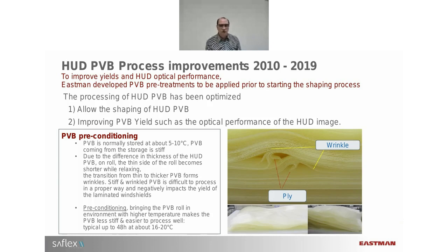So if you just cut the PVB from roll to sheet size, there is a high probability that you obtain wrinkles and, in the worst case, even plies. Wrinkles can cause optical distortion. And of course, a head-up display is a projection system. So the last thing you want is having optical distortions. And plies can do the same, but even worse, in some cases cause glass breakage.